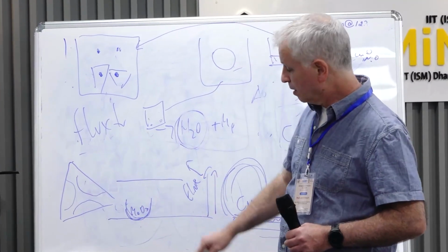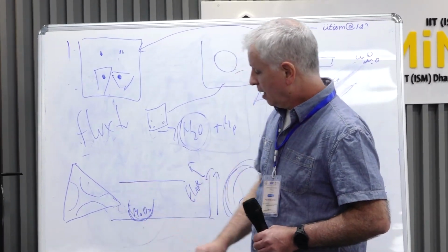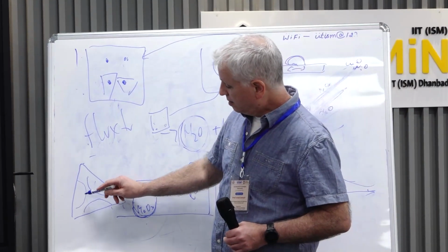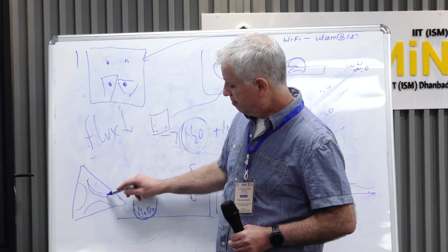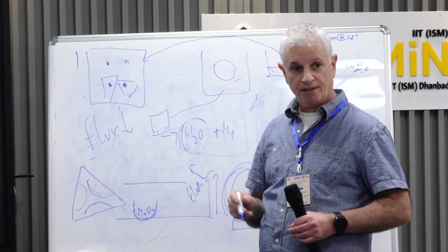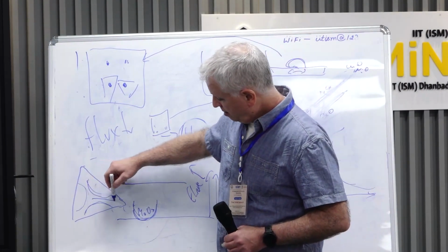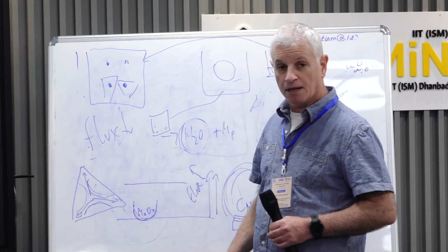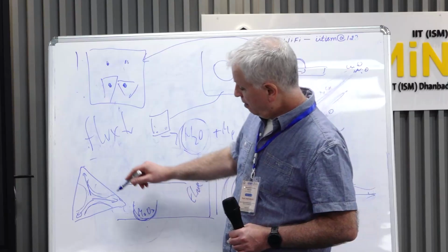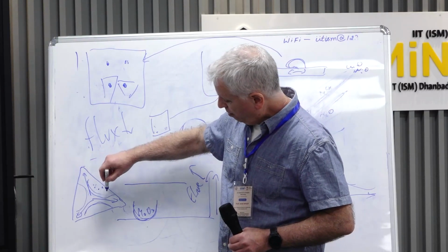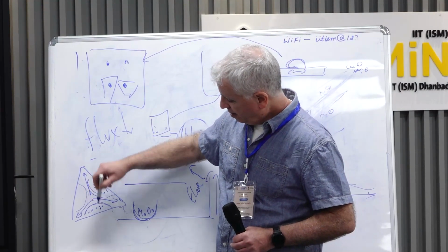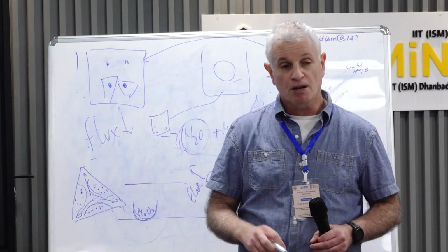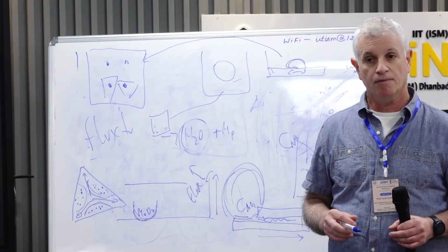So we got triangular domains, and when we did PL mapping, we saw very clear different areas with different PL. This different PL was because these areas were full of gold dots.